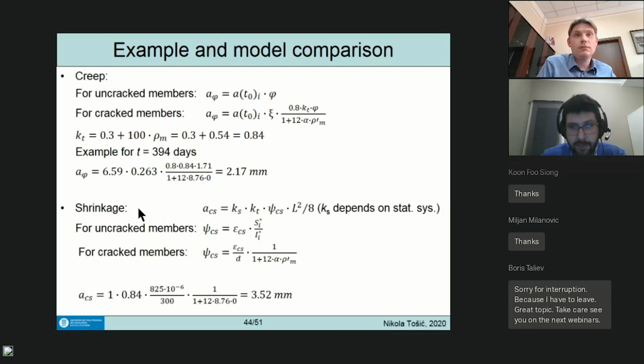And from shrinkage, it's a separate value because it's independent of load. It's Ks, a coefficient depending on the statical system: 1 for simply supported beams, 0.7 for edge spans of continuous beams or slabs, and 0.85 for interior spans. Then KT is the same coefficient as before.